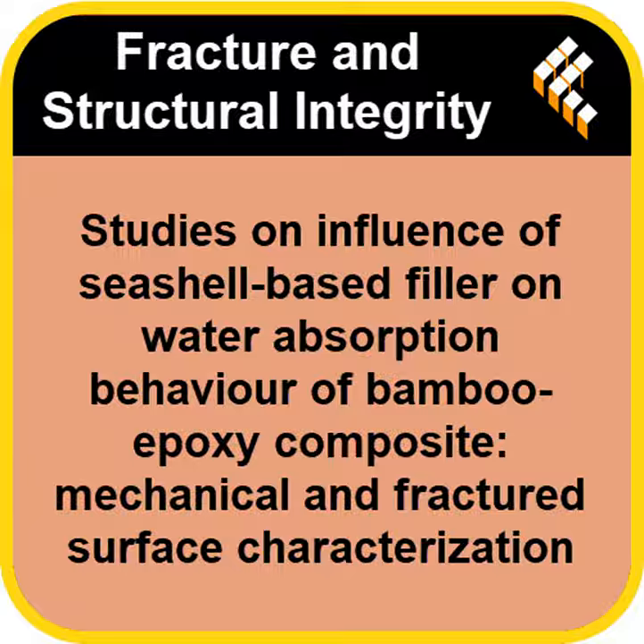How did they put it all together in the composites and test them? Right, so the bamboo fiber content was fixed at 35 weight percent for all samples. They then made 4 different batches. One was the control, just bamboo and epoxy, 0 filler. The baseline. Then they made 3 hybrid composites, adding the clamshell powder into the epoxy at different levels, 3%, 6%, and 9% by weight.